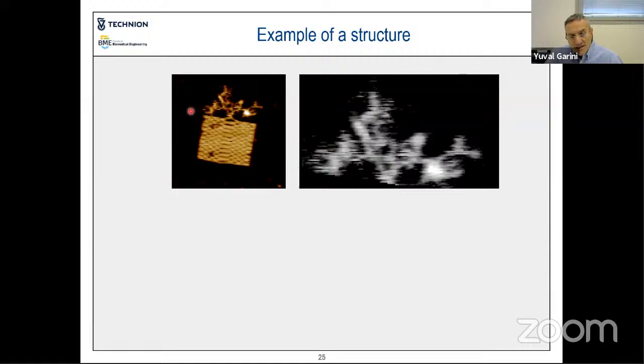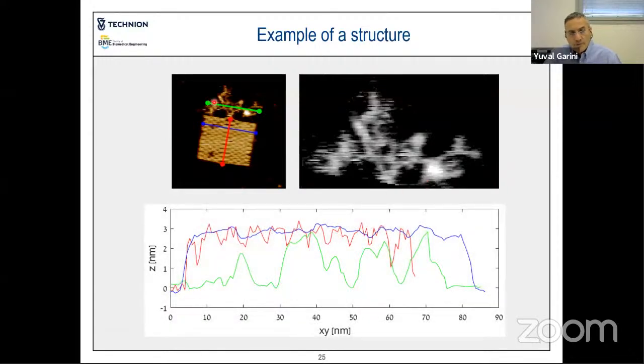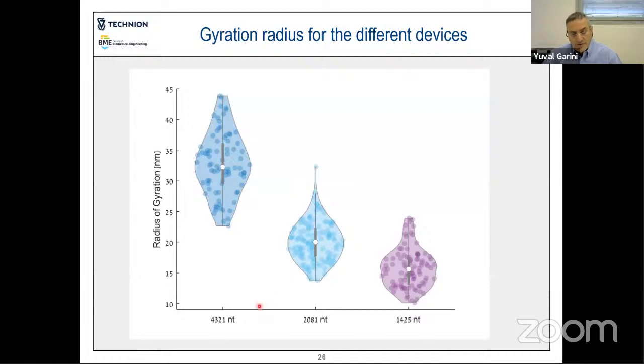So this is a zoom in just to the single-stranded ring polymer and the way it is shown with the atomic force microscope. And when we look at along different points here, we can see that there is a very reasonable distribution of the DNA along those structures, and it can be measured. So the gyration radius can be calculated from what we see here. And for three different structures that each one has a different number of nucleotides along the ring chromosomes, we calculated the distribution of the gyration radius. You can see that it makes sense that it becomes shorter as long as the number of nucleotides is shorter.